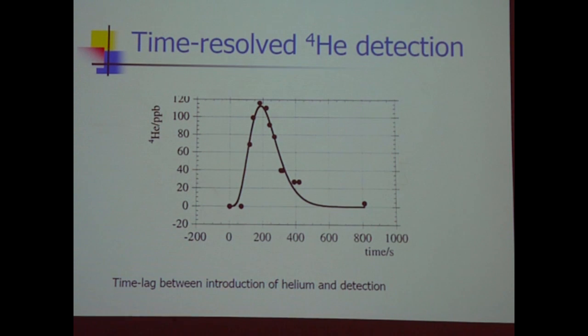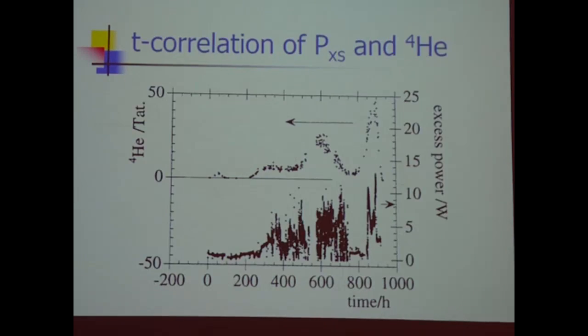They set things up such that they could sample in real time. And here's an example of measurements done, showing that at t = 0, they put some helium into their system, and at 200 seconds, 400 seconds, you could actually see the helium, so it's now time correlated with the production. So the idea is that if you have a heat burst, when the heat burst happens and you measure helium, if you correlate the helium in time with the heat burst, that's interesting. That would be reasonably convincing. So here's data, and here's time in hours.